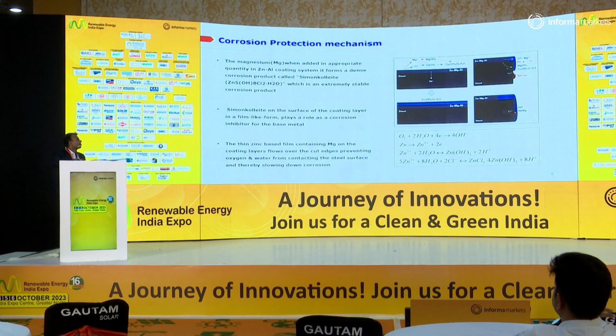So, coming to the corrosion protection mechanism. Unlike GI, where normally zinc oxide forms, which is porous and non-adherent, here simonkolleite forms, which is very stable and adherent to the coating layer, and this even flows to the portion where cross-section cut edges will get red rust at the initial stage. So it will cover those portions and will protect the steel substrate underneath. Secondly, this itself has very high hardness, so it gives protection when it comes to scratch resistance.